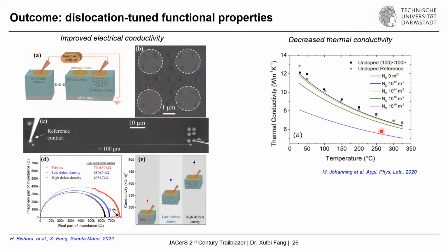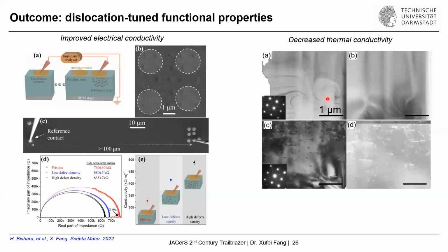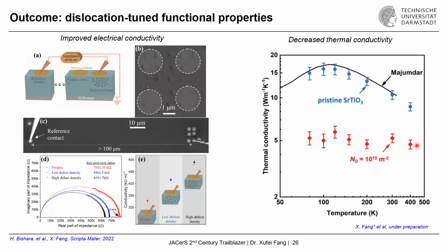So in literature, it has been predicted that we need a dislocation density of almost 10 to the power 15 per square meter to see an impact of dislocations on reducing thermal conductivity. And all these dots here are the experimental data, which actually have a rather low dislocation density, so a decrease of the thermal conductivity was not really seen. And in our case, as I showed just now, we were able to engineer a density up to 10 to the power of 15 per square meter, which now shows us a very appreciable decrease of the thermal conductivity, even by almost 50% compared to the pristine samples.